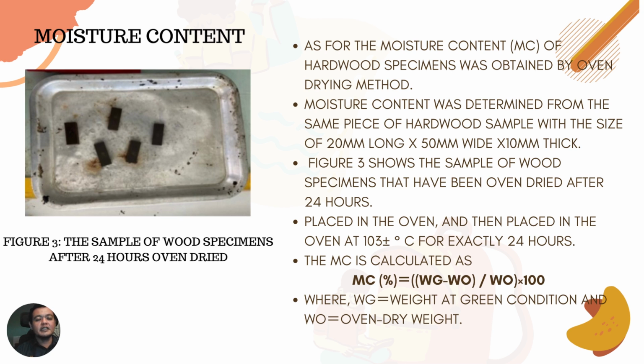To carry out this experiment, the wood sample must be weighed before being placed in the oven at 103 degrees Celsius for exactly 24 hours. The moisture content is calculated in percentage: weight at green condition minus oven dry condition, over oven dry condition, times 100%.